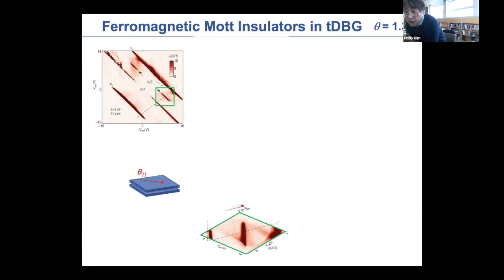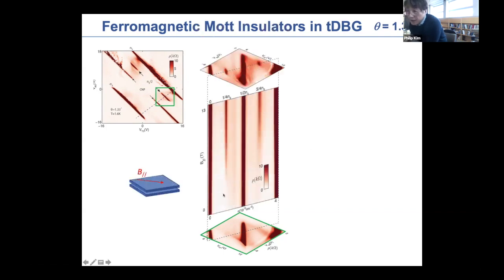It turns out when you apply the in-plane magnetic field, this half filling gap that I just mentioned becomes much stronger. The size of the gap actually increases. Not only that, previously we didn't have any signatures on the quarter filling side. Applying the in-plane magnetic field, we actually start to stabilize this gap in the quarter filling states. So in a sense, there is a half filling gap and quarter filling gap states, which appears very similar to the magic angle twisted bilayer graphene.